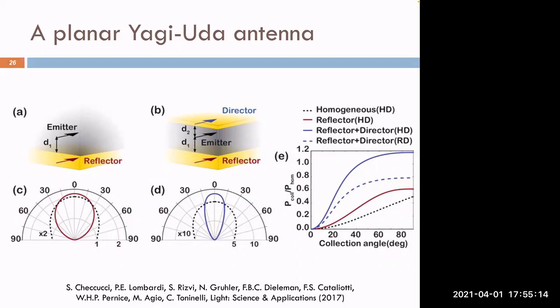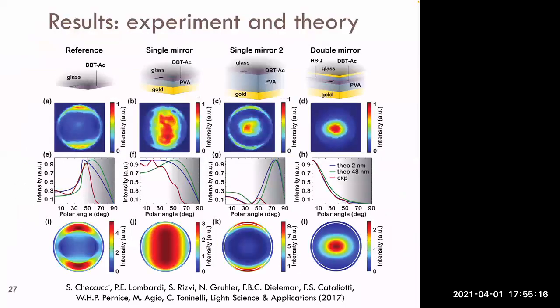And let me show you the experiment because this is much easier to understand. So you see in the left column, the case of a molecule on glass. You see the emission pattern is very bad, actually. So you have the emission at very large angles. So these two-dimensional plots are essentially Fourier images of the emission, so basically the radiation pattern. So the circle is because your objective has a limited numerical aperture, okay?